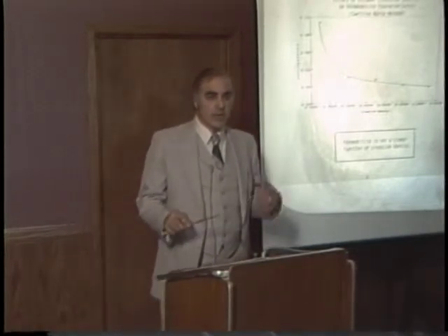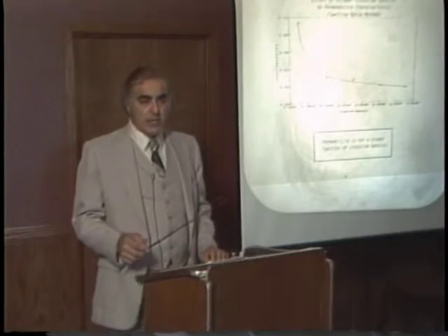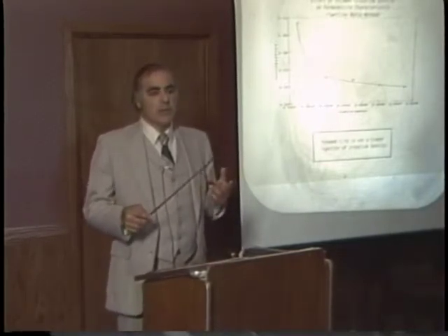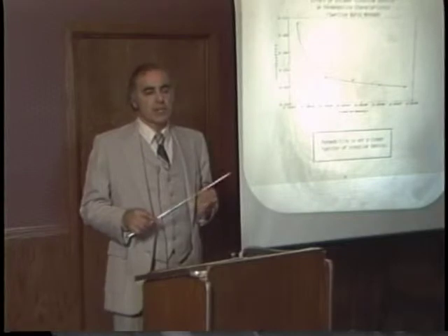and not affect the permeability characteristics very much until you get to the very low end where the material is very slightly cross-linked. And it indicates that the permeability is not a linear function of crosslink density. The reason for this is not too clear. It may have something to do with a threshold molecular volume within the network that allows materials to migrate rapidly once a certain molecular size is reached when you remove the restraints of crosslink. Next slide, please.